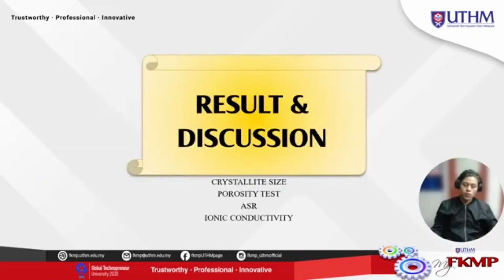And then lastly, the electrochemical testing at the temperatures 600, 700 and 800 degrees Celsius. The frequency used is 1 Hz, and the AC voltage amplitude is 10 millivolt. Okay, next we go to the result and discussion. In the result and discussion, we discuss crystalline size, porosity test, ASR value, and the ionic conductivity value.